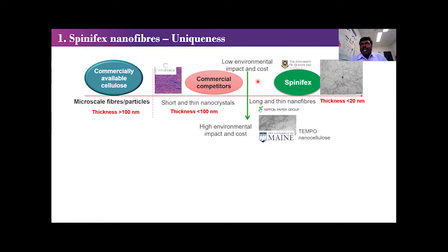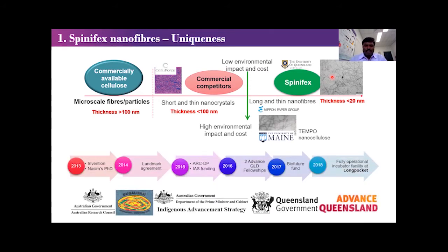Or if you want to have a nanofiber, something like this, you have to do other oxidizing treatments. So our spinifex, without any such treatments, we could get that long and thin, tough nanofiber. We started around 2012, and now we've got a few grants from the federal government and state government, and we had a partnership growing in the last 8 years. Now we are fully operational at pilot scale, so we can produce nanocellulose at about 5 kilos a day.